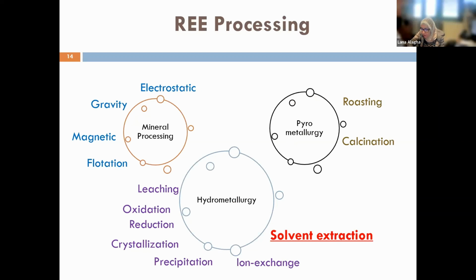Again, gravity separation is suitable as a beneficiation technique for rare earth physical separation, due to the relatively large specific gravity of rare earth minerals or rare earth bearing minerals compared to other associated gangue minerals such as silicates, for example. One of the most famous flow sheets where gravity separation is used is when you process beach sand. You apply gravity separation to remove heavy material, using spiral concentrators to produce a heavy concentrate that contains heavy minerals.